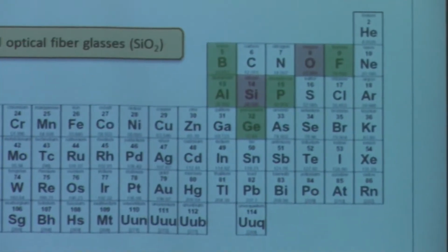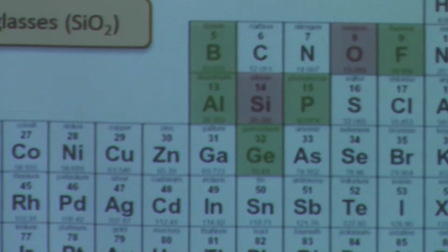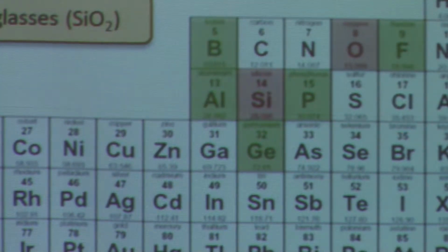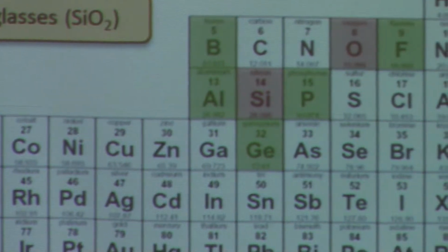because it's available and cheap. And then you begin to add certain things into it depending upon what properties you want to influence. Fluorine changes the viscosity of the melt, and it changes the optical properties. Phosphorus raises some of the optical properties, such as refractive index, and it lowers viscosity. Germanium raises the index, doesn't do a whole lot to anything else. Aluminum and boron change the glass structure a little bit, make it more fluent, and drop the melting temperature and the glass transition temperature.